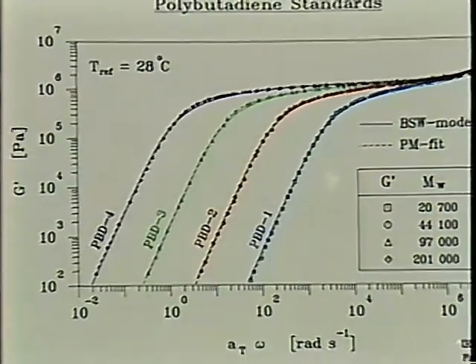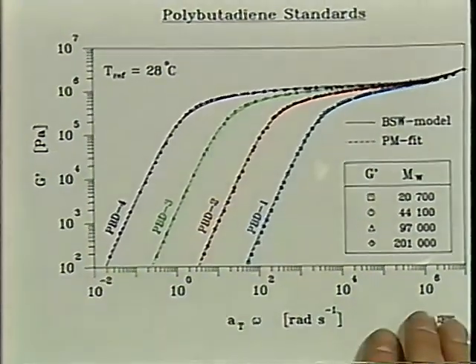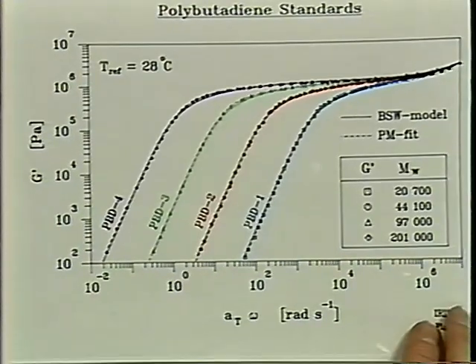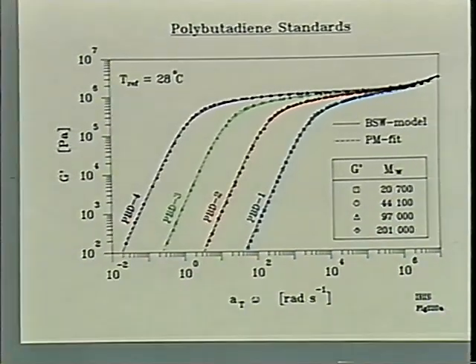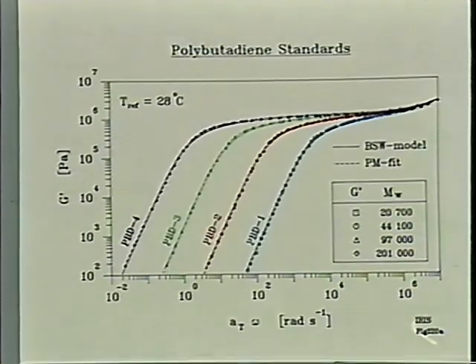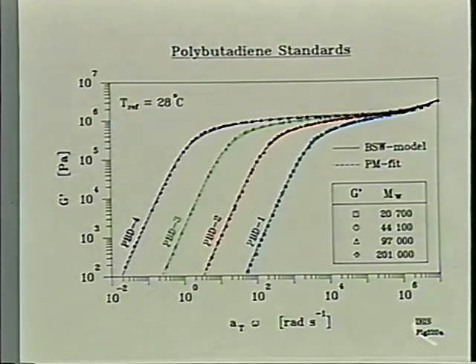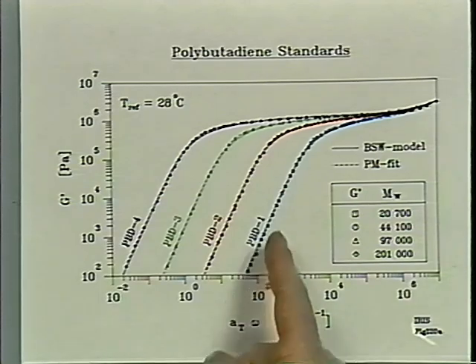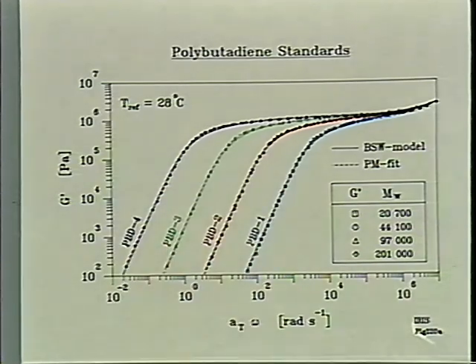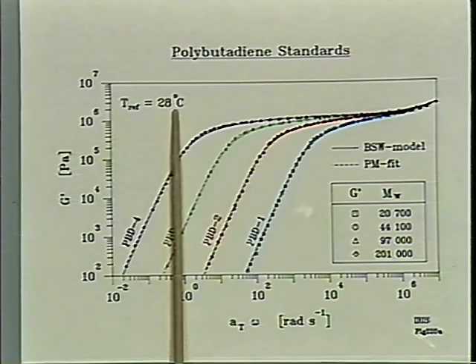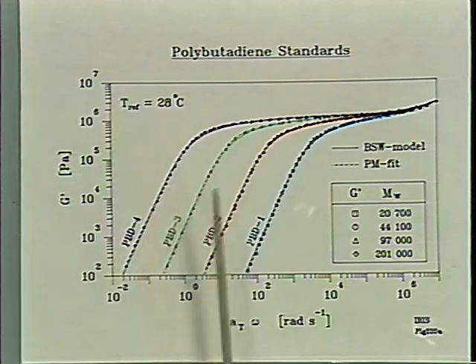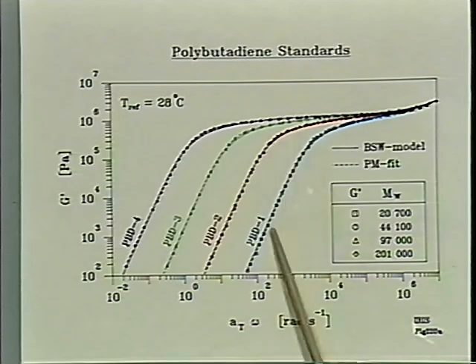This is the experimental data set, G prime, of a monodispersed polymeric material. This is polybutadiene standard measured by Mike De Rosa. G prime at 4 different molecular weights. This is the highest molecular weight, having a breakpoint at low frequency, at long times, and then at shorter and shorter times as the molecular weight is smaller and smaller. The counterpart is the loss modulus, as shown here.